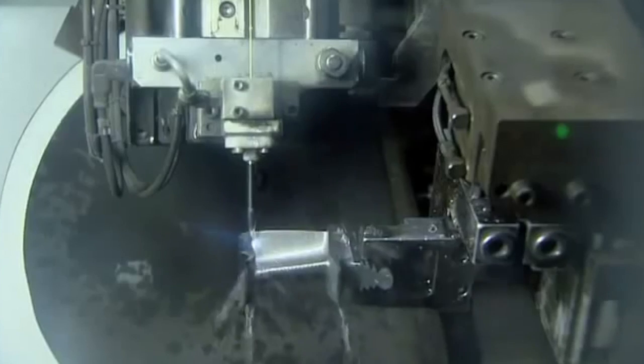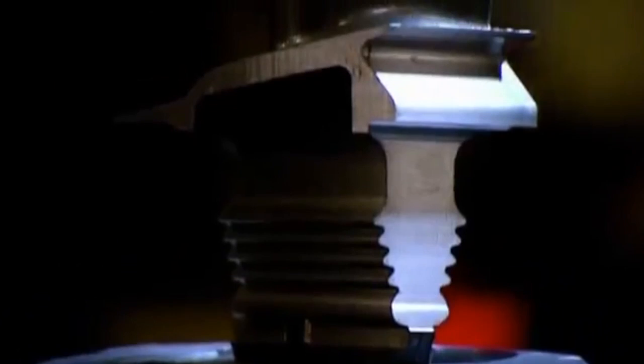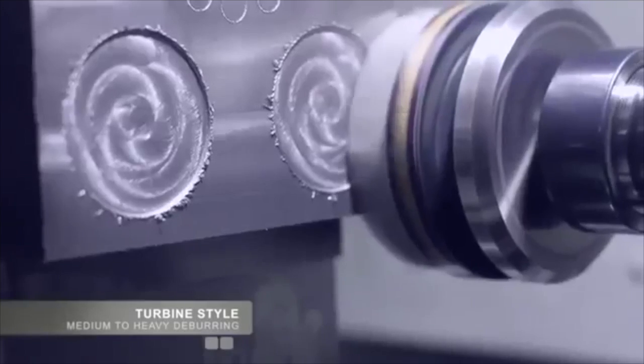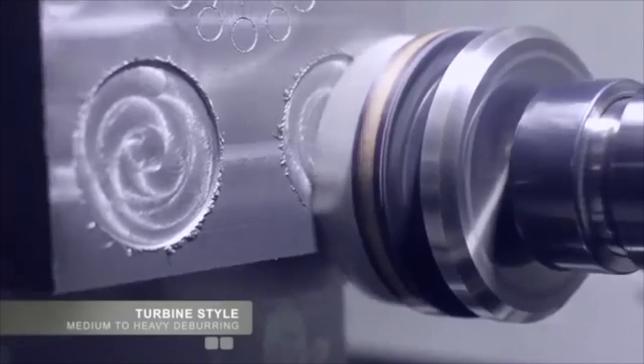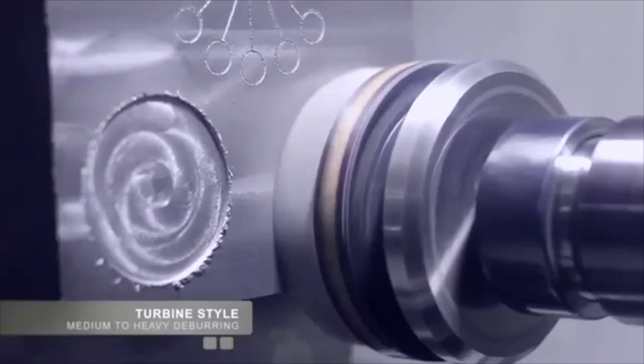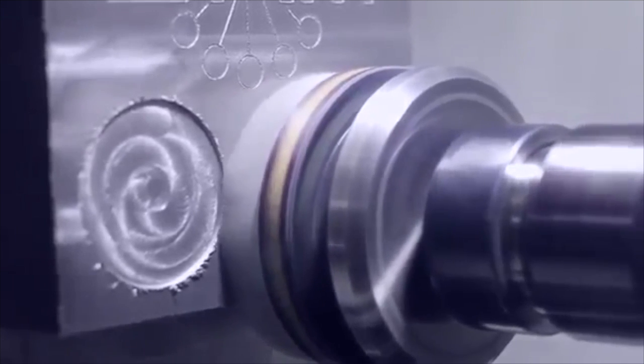They firstly have cooling holes drilled and then have the fir tree slot profile ground to a tolerance of 5 micrometers. This is where the machining processes end and the finishing process begins. The burrs arising on the edge of the turbine blades during machining are removed in the same process without having to go to a different machine.